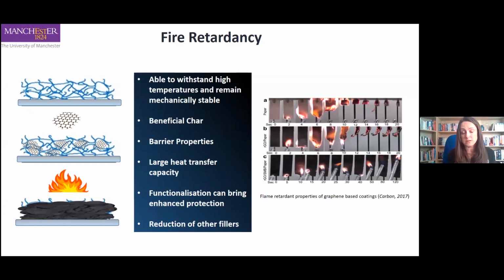High organic fillers can tend to lead to aggregation and dosing issues. Also, you can use it in conjunction with other materials. So you might get a synergistic effect where you end up using less of both materials to get a bigger benefit. Graphene's non-toxic. You're not going to get those toxic byproducts that you would from other flame retardant constituents. One of the ways it works to help with these coatings is it forms a beneficial char. It's got a unique aspect ratio and it's got a layered nature, and you get this char that's formed is dense and it's continuous.